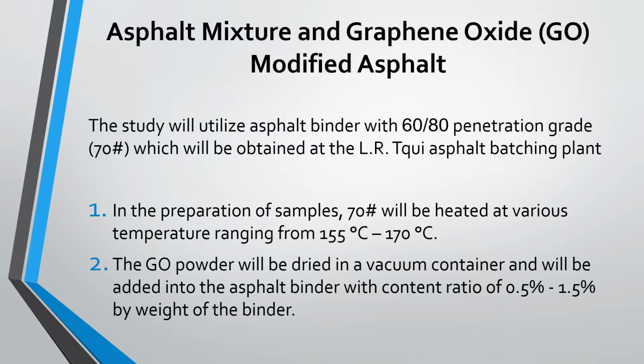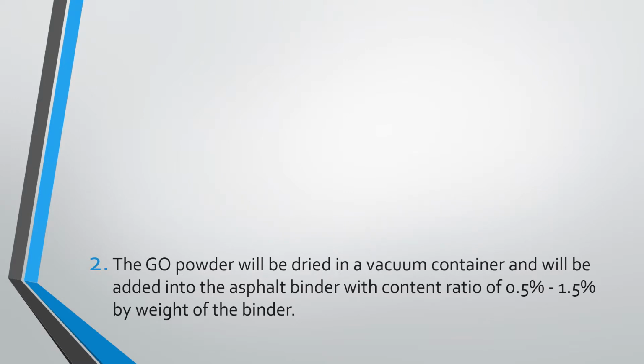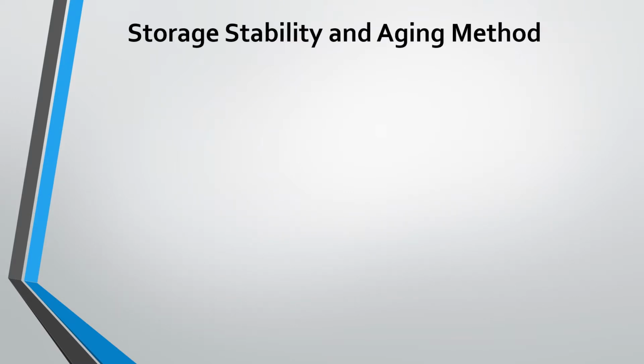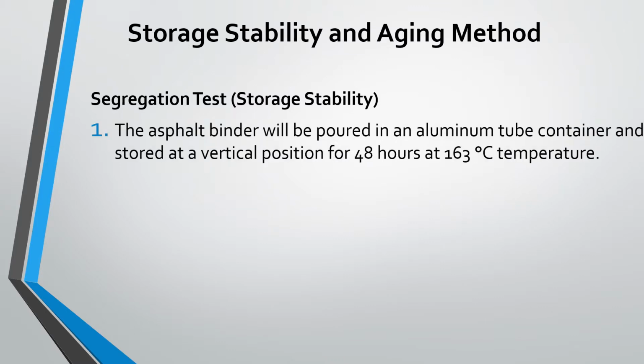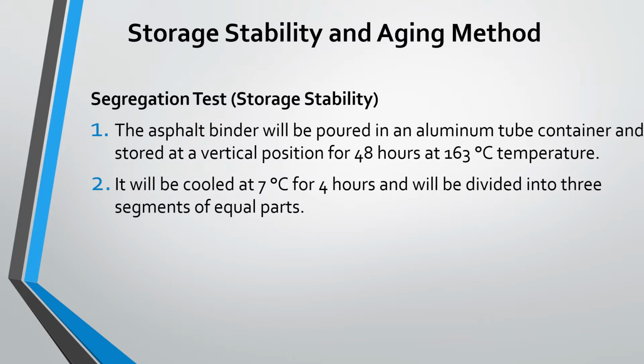In order for us to determine the storage stability of the GO-modified asphalt, a segregation test will be used. The asphalt binder will be poured in an aluminum tube container and stored in a vertical position for 48 hours at 163 degrees Celsius. It will be cooled at 7 degrees Celsius for 4 hours and divided into 3 segments of equal parts.